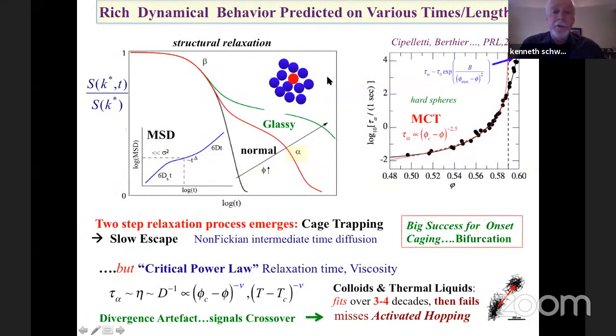Rich dynamical behavior is predicted by the mode coupling theory as a function of time and length scales, and here are two prototypical results. The first is the dynamic structure factor, normalized at time equals 0, on the scale of the cage versus the log of time. So this is a schematic, but if the temperature is high enough or the density is low enough, then you get a simple relaxation process that's roughly exponential. As you increase the packing fraction or lower the temperature, you get a bifurcation. You get two processes and you begin to get a plateau.